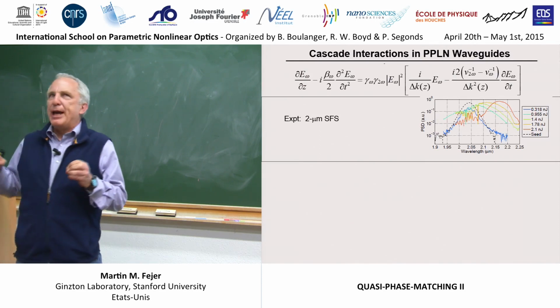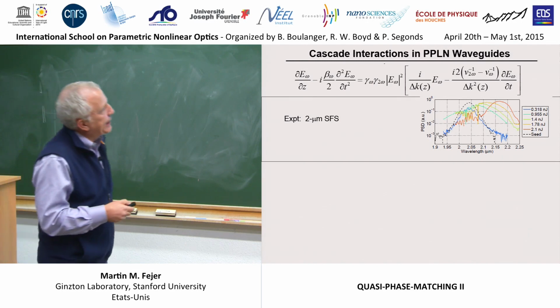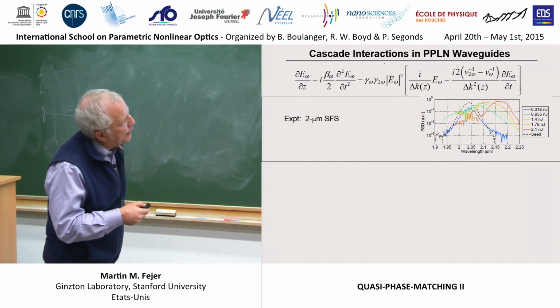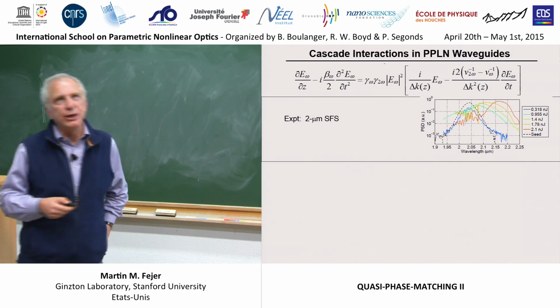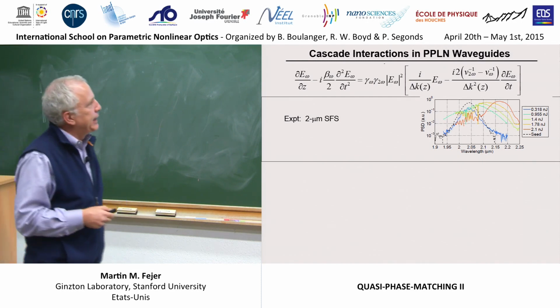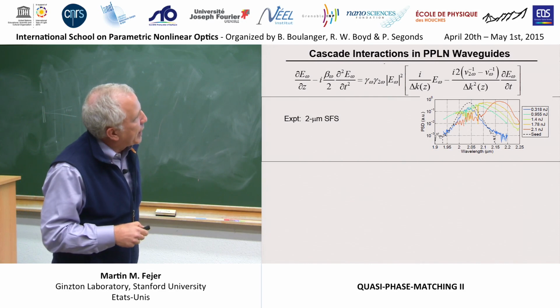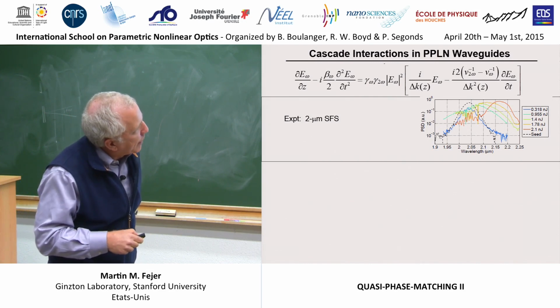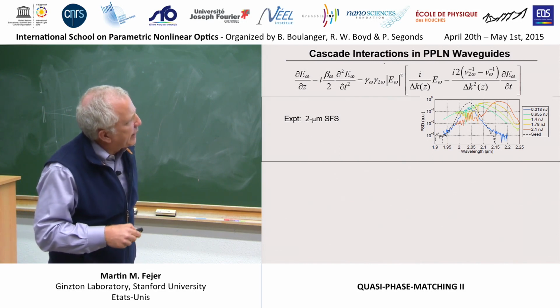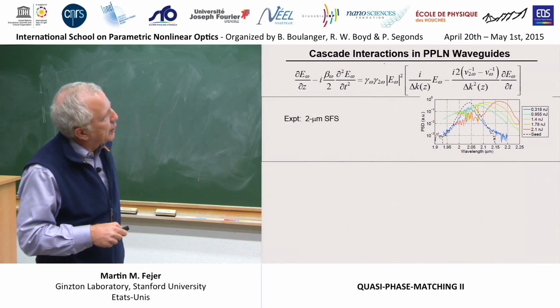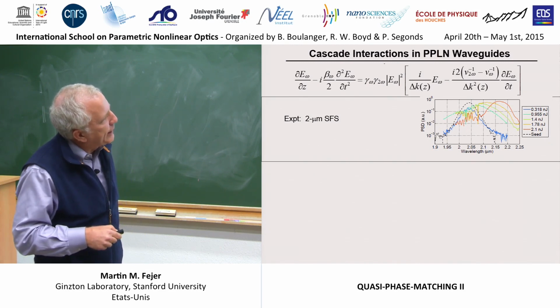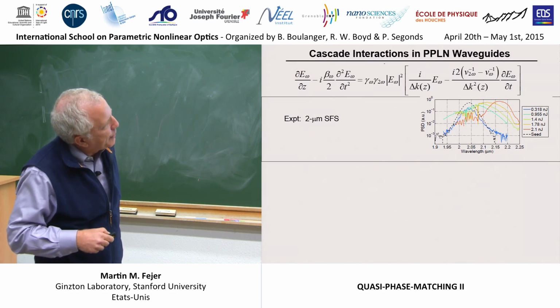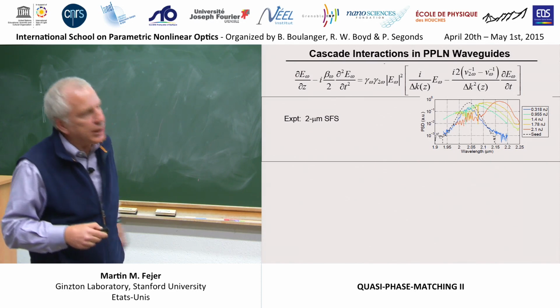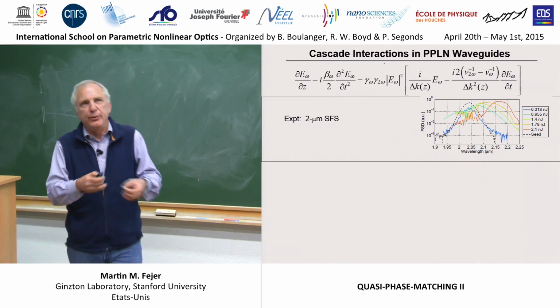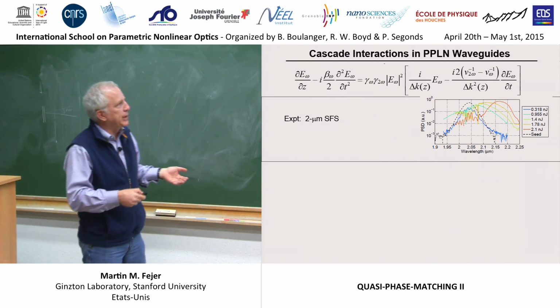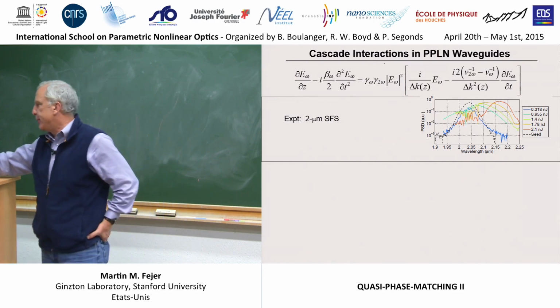Just a couple of other examples of this kind of thinking. I said there is a cascade Raman-like behavior that emerges from this multiple scale analysis. This is an experiment where 2-micron radiation of, I think, about 150 femtoseconds was launched into such a waveguide. And as you turned up the energy in the pulse, you see something that looks just like a Raman self-frequency shift. But with the real Raman coefficient of lithium niobate, you'd see nothing like this. It's not nearly big enough.